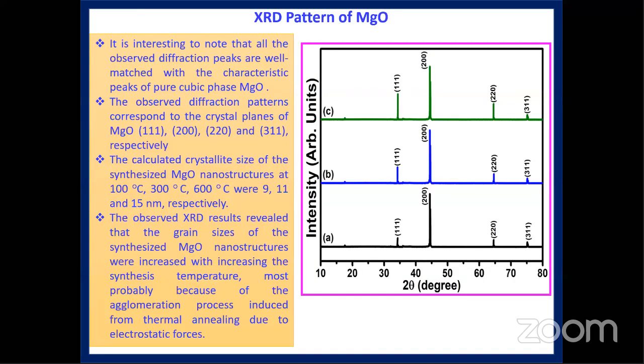You can see here the XRD pattern of MgO nanostructures at different temperatures. The XRD pattern A is 100 degrees Celsius, B is 300, and C is 600 degrees Celsius. You can see the planes indexed as 111, 200, 220, and 311. These planes correspond to the cubic structure of magnesium oxide. From this XRD, we can also confirm whether the material is crystalline or polycrystalline. You can see here the well-known peaks that we observe, so MgO has a crystalline structure.